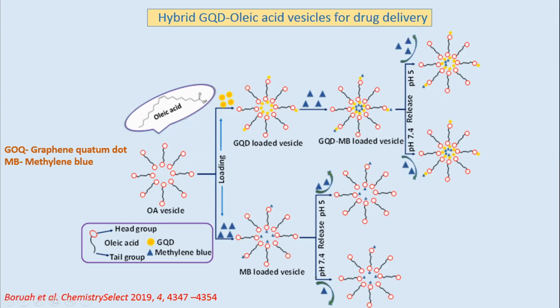So finally, I prepared oleic acid vesicles. Then I attached carbon-based nanoparticles. Here, graphene quantum dot is attached to the surface of the vesicles. Then finally, I used methylene blue as a standard or model drug, and I attached this methylene blue to this composite system, and then I studied their release profile. So finally, I used a pH sensitive drug release system, and you can see that at 2 different pH, especially at pH 5, this system can release drug, but not at 7.4.